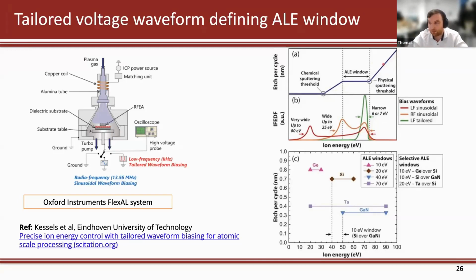And sputtering the materials. And you can see here, you can get very wide peak splitting with the general RF biases. So that means you have some ions in the window doing the work, some ions outside doing nothing, or worse, you could have some ions in the window doing what you want and some doing damage. Okay, so you want to have a single peak. Okay, here's actually there's nice measurements of what these ALE windows are for different materials. So these are things you should kind of keep in your back pocket if you're doing this sort of research.